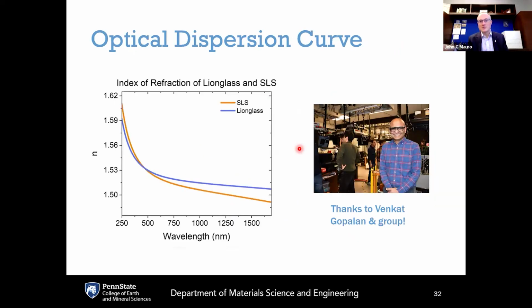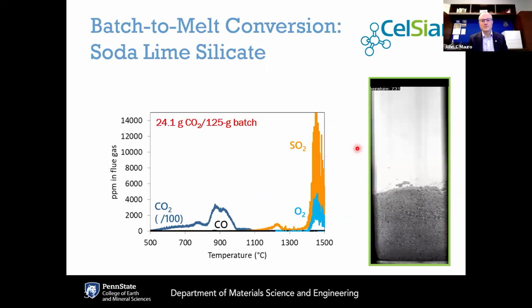What if you just look at Lion Glass? Can you tell the difference just by looking at it? The refractive index profile is very similar between Lion Glass and soda lime, so there's no difference there. The one thing that you might notice is that Lion Glass is clearer. Soda lime has a little bit of a greenish tint to it, and that greenish tint comes from iron contamination. Lion Glass is actually a lot more resistant to coloration, so it gives more of a pure, perfectly clear color as opposed to this greenish tint.